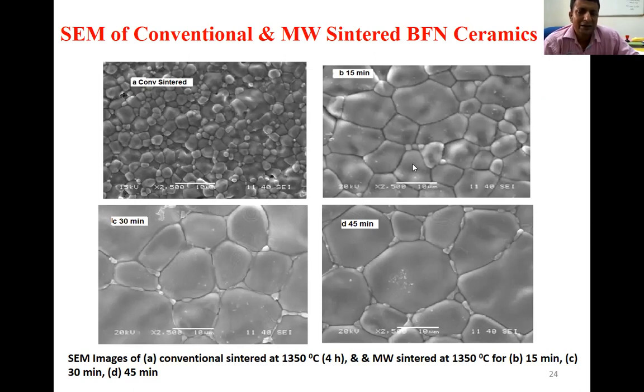But as I told, it's material specific. In general, mostly we get the small grain size, but here in the case of the BFN, they are good microwave absorbers, and even in small time durations the grain growth is rapid actually, so we got bigger grains. That is what we observed.